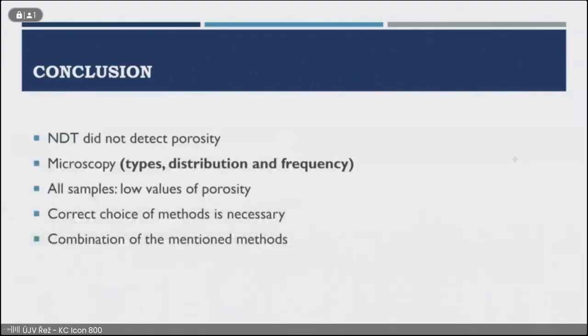So in conclusion, any non-destructive testing did not observe any presence of the pores, but only microscopy did observe pores. Microscopy also told us about types of pores, distribution, and frequency. But microscopy isn't the best choice for detection, because with microscopy we can only see a tiny plate from all the volume of the sample, and a better choice is to combine destructive and non-destructive methods of testing.